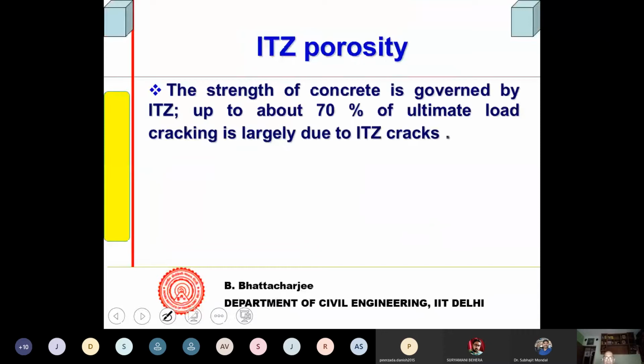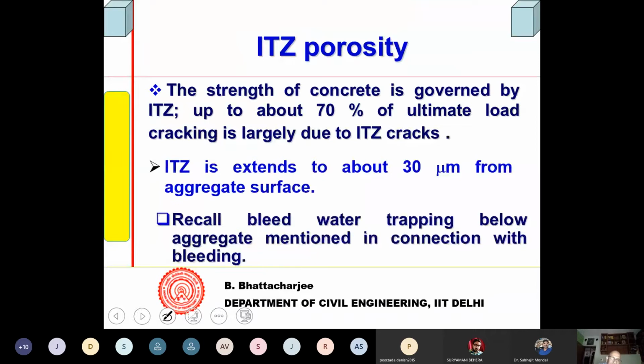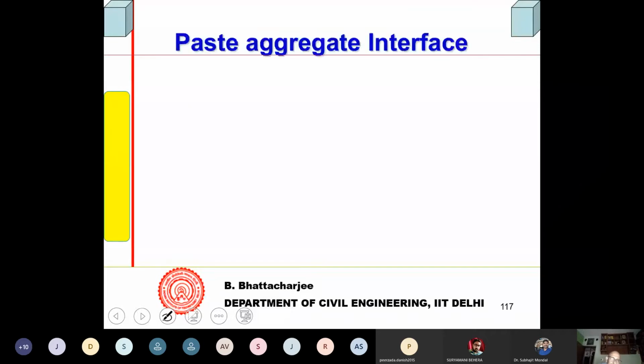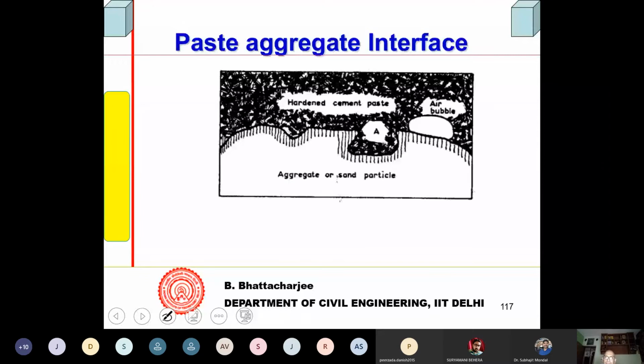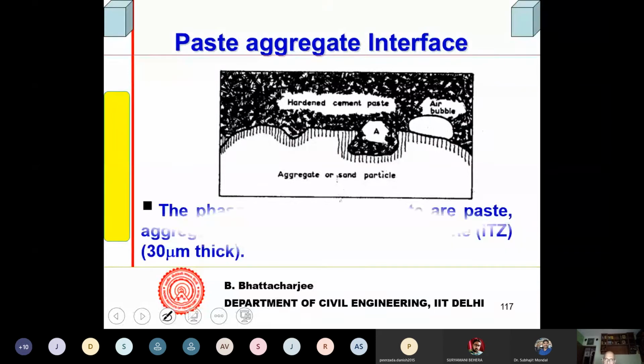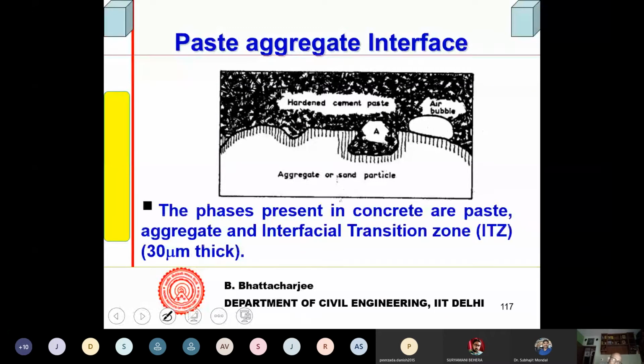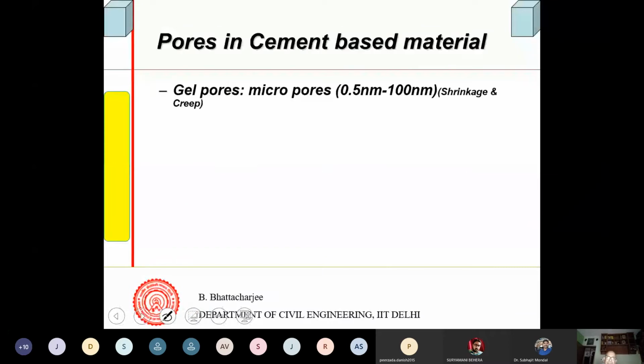But in concrete, you have additional porosity at the interface of the aggregate and paste. Something like this, this diagram will give you. Paste, aggregate bond, aggregate particle, paste. So these are mechanical bond. There will be air bubbles trapped here. There will be more porosity, wall effect, and shrinkages here, no shrinkage on this side. Hydration from that side, hydration on this side is little. This is around 30 micron. So this added additional pores, and we don't know how to quantify them as yet.